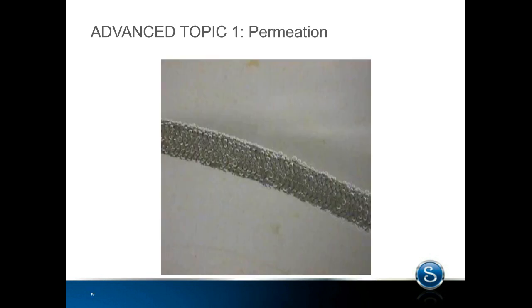And what permeation tends to look like in a hose, this is a hose submersed in water, and this is just virgin Teflon, so there was no sintering process on this particular hose, so it's permeating at a bit of a higher rate. And all along the length of the hose, it appears to be leaking because you get these bubbles on the outside of the braid. And technically, I suppose it is leaking because permeation could be considered a leak, but there is no crack in the hose. There's no failure point. It's just permeating whatever, I think this was nitrogen, out of the hose, and the gas bubbles are collecting on the outside.